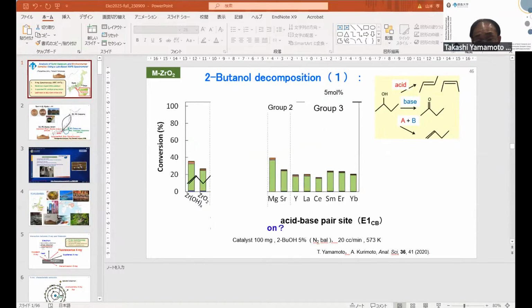Firstly, we use butanol decomposition reactions. This is a test reaction to investigate the acid-base properties. This is the secondary alcohol. Typically, if dehydration occurs, usually the inner olefins should be formed, following the Zaitsev orientation. But in a case where acid and base sites coexist, alpha olefins are formed, which is the difference.